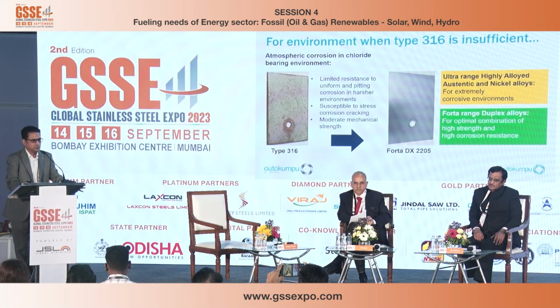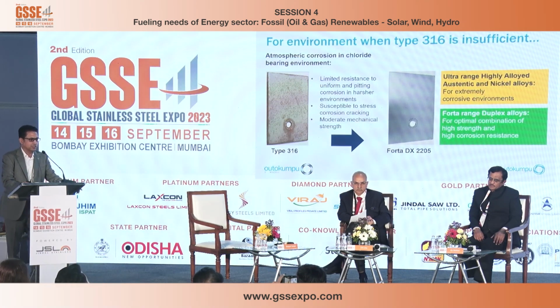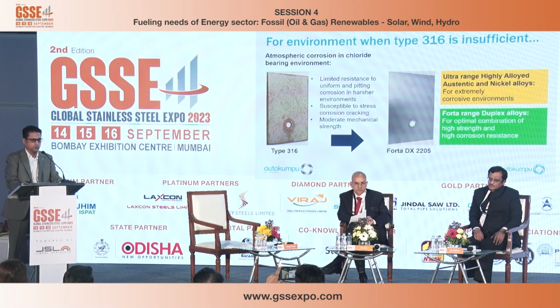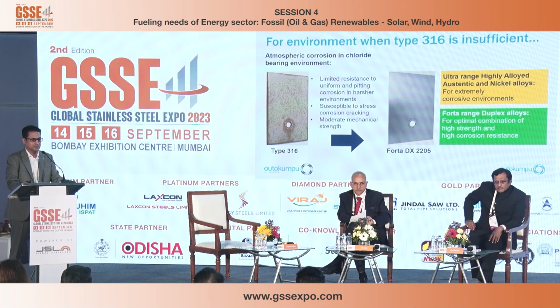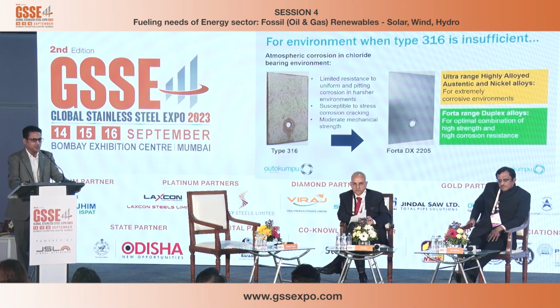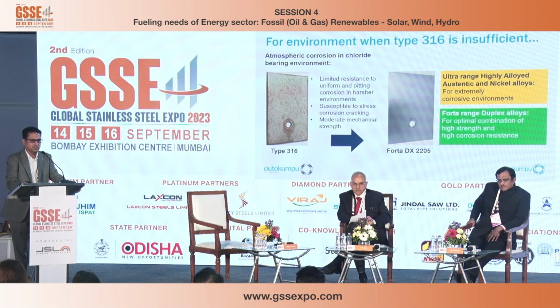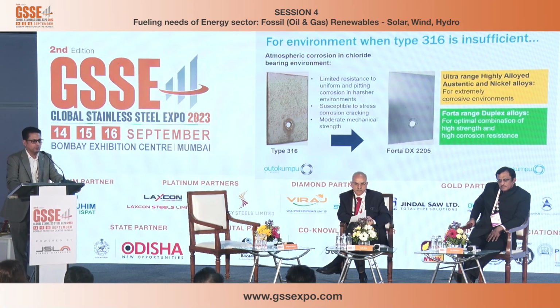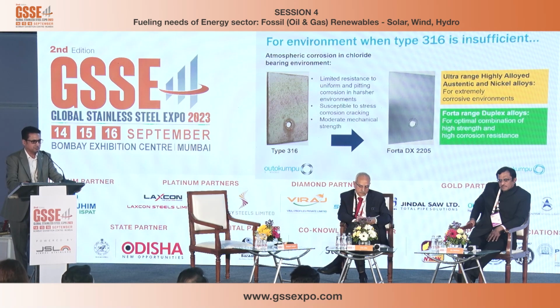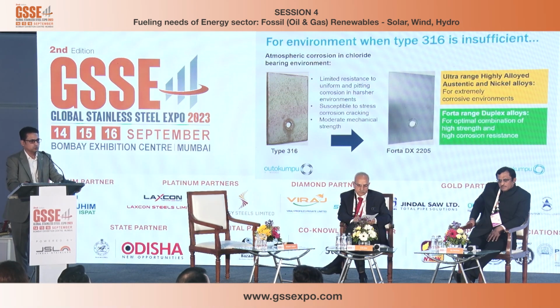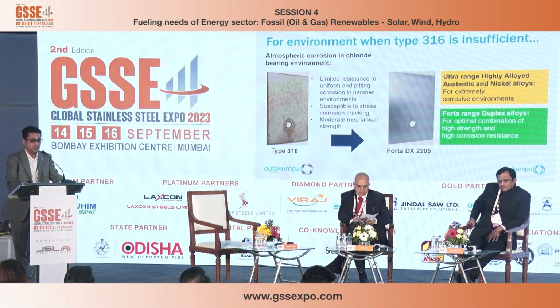So you will see two pictures over here in the same environment. On the left hand side, you can see the 316L, which has corroded after a couple of years, and on the right side, in the same environment, you see duplex 2205, it is still clean. The issue with 316L is it has a limited resistance to uniform and pitting corrosion in harsh environments, and it is susceptible to stress corrosion cracking, and has very moderate mechanical strength in comparison to some other materials. So there are environments where 316L is not sufficient.